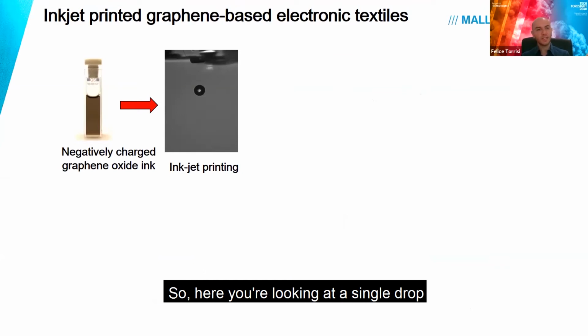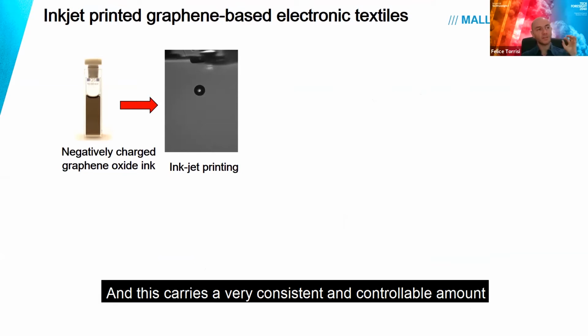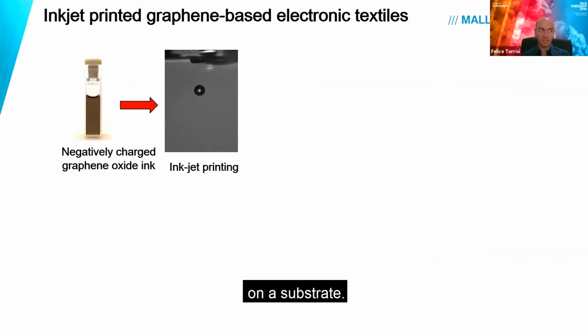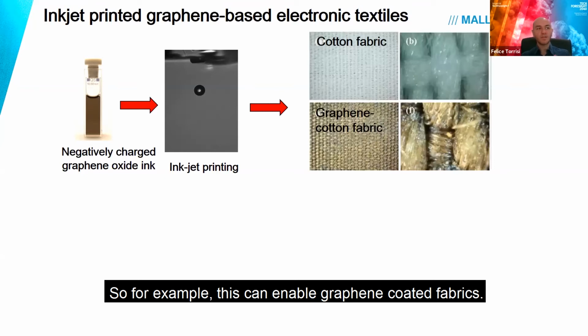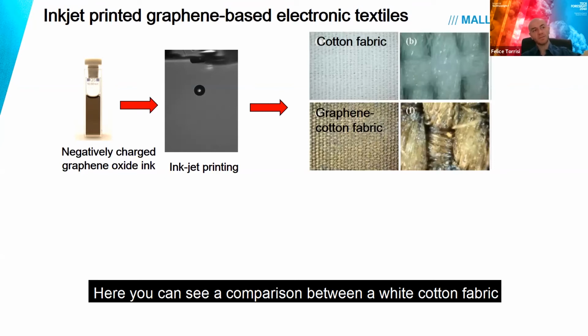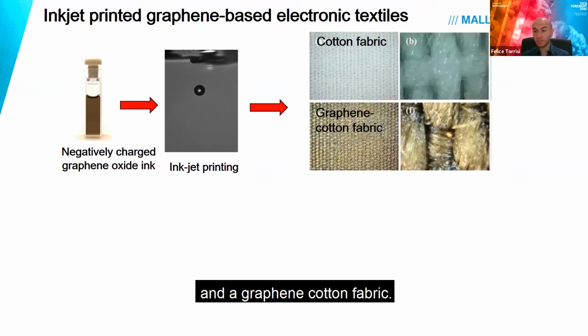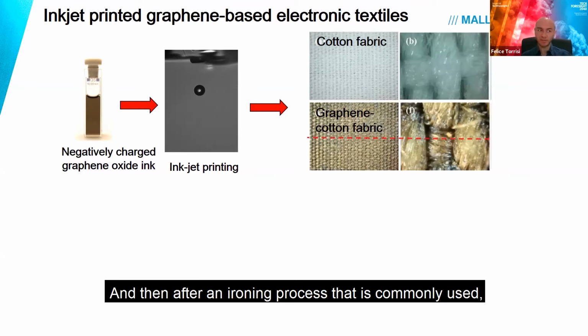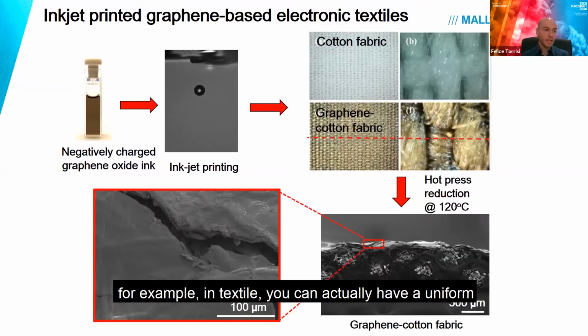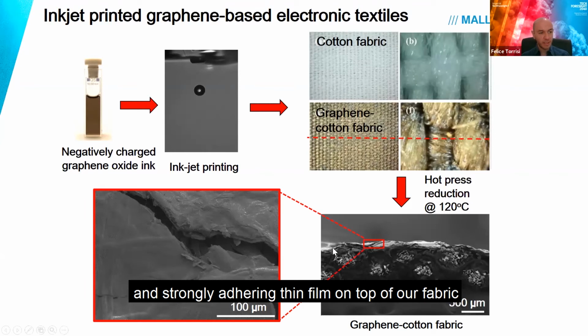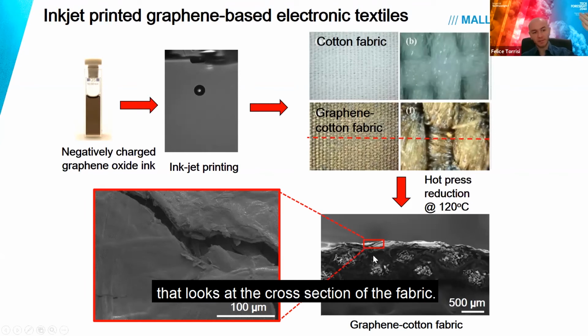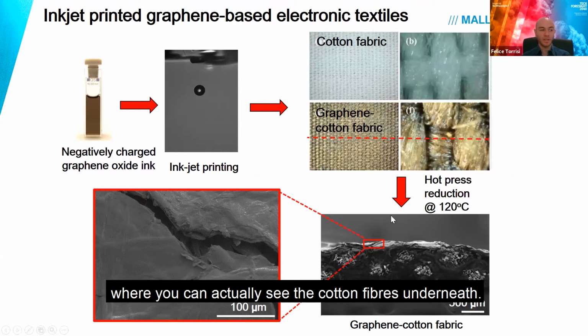Then I took my negatively charged graphene ink and, for example, I formulated it for being printed by inkjet printing. So here you're looking at a single drop generated by an inkjet printer nozzle, and this carries a very consistent and controllable amount of graphene that you can deposit regularly, drop on demand, on a substrate. So for example, this can enable graphene coated fabrics. Here you can see a comparison between a white cotton fabric and a graphene cotton fabric. And then after an ironing process that is commonly used, for example, in textile, you can actually have a uniform and strongly adhering thin film on top of our fabric, seen in the cross section of the fabric. And here you can see the top view, there is a thin coating on top of the fabric where you can actually see the cotton fibers underneath.